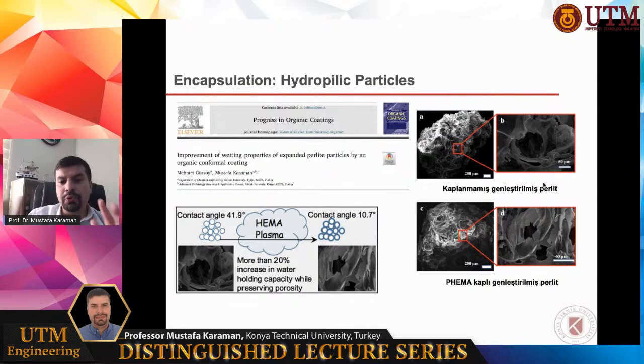we improved the wetting properties of the expanded perlite by a very thin organic coating, again, under the PECVD conditions. So you can see after the coating, the geometry of the perlite surface doesn't change. What changed? Only the chemical structure. Only a few nanometers of thin film are deposited on the surface, which change the whole story. Make the material hydrophilic, hydrophobic, antibacterial, conductive, anything you want. Here we showed the improvement in the hydrophilic properties of expanded perlite.